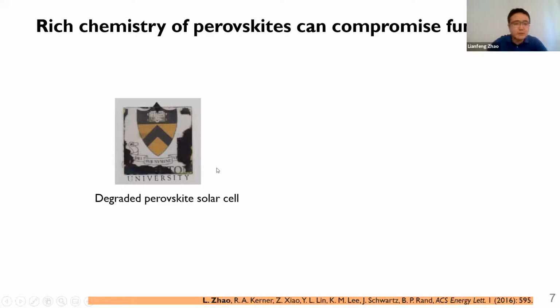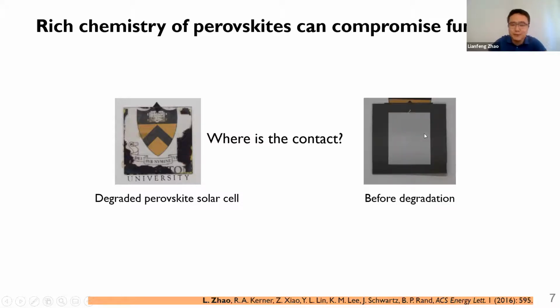Actually, there's rich chemistry in perovskite. I will start with an extreme case here. So this photo is a degraded perovskite solar cell. One natural question would be, where is the contact? You know, for any electronic device, we will need an electrode, but where is it? Actually, this is the photo of the device before degradation. It is a big aluminum contact at the center, which has become transparent after device degradation.